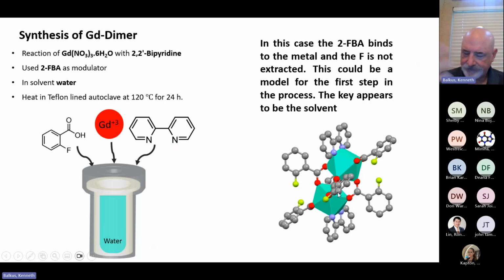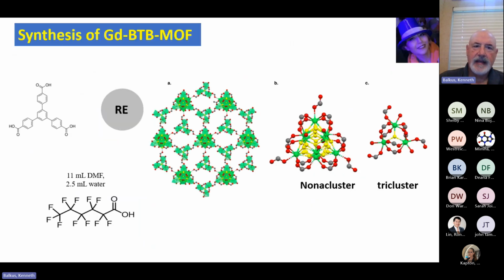And in fact, if you take this cluster now, this dimer with 2-FBA bound, and you heat it up in DMF, it forms this structure. Okay. And in this particular case, you end up with this linker, which has 3 carboxylates on it. And I should point out, this is interesting how we got into the PFAS.